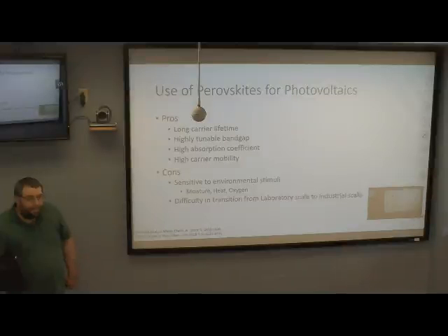Typical lifetime: they've increased it to about a year right now, but it's not uncommon for half a year. For two-dimensional perovskites or regular? For two-dimensional, it's about a year. And for regular, just for comparison, 3 to 6 months. It's very optimistic. It depends on how well they manage to protect it from water.